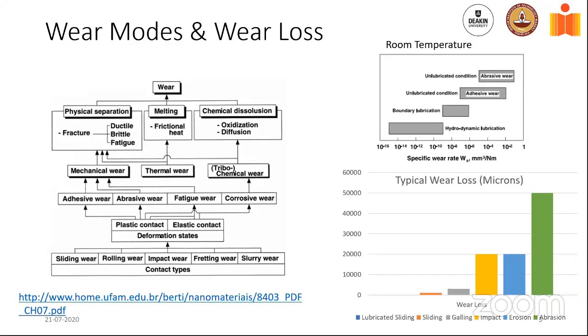And the graph on the bottom right, which shows abrasion, erosion, impact, galling, and sliding, kind of tells you what is the difference in terms of wear through these different mechanisms. When you're looking at lubricated sliding, it's in the range of 10 microns. When you're looking at impact, it can be as much as 20 millimeters or 20,000 microns. When you're looking at very heavy duty abrasion, which is the green graph on the right, you can actually lose 2 to 3 inches of material, which is around 50,000 microns of material.